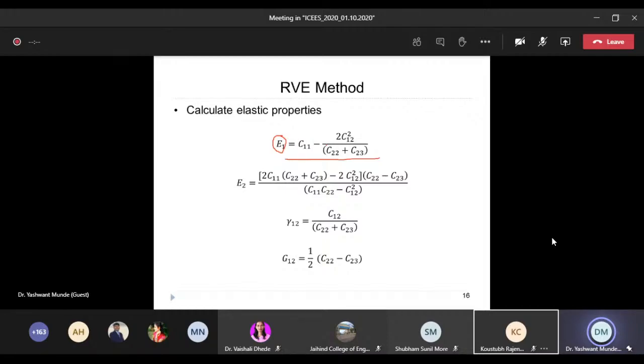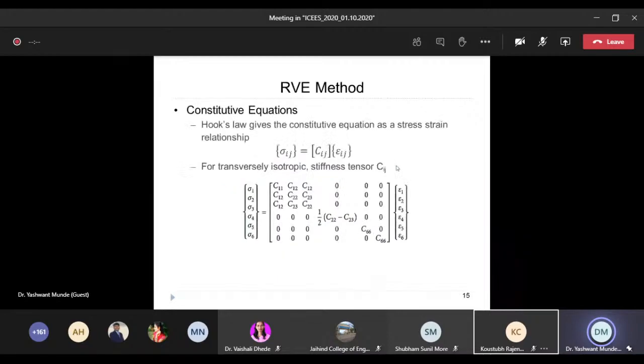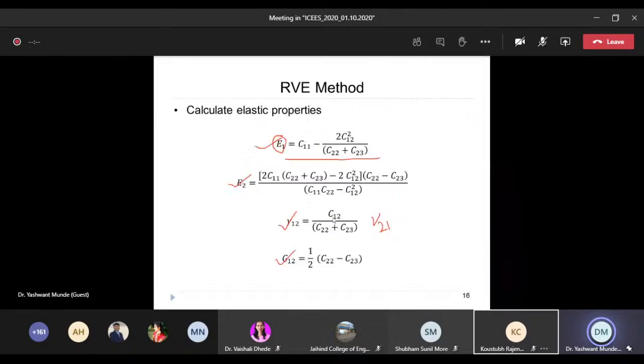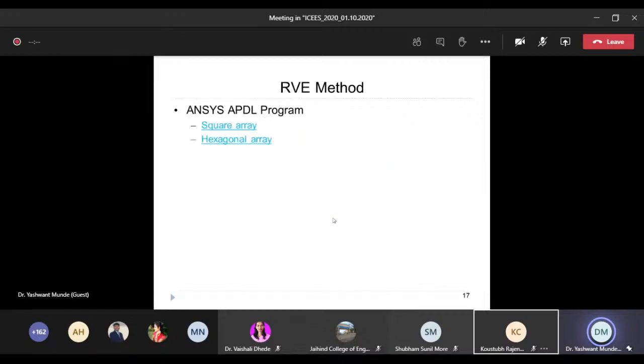And those CIJ coefficients we use to calculate the elastic properties of the composite material. That is E1, the elastic property of the material in direction 1, E2, the modulus in direction 2, mu12, Poisson's ratio in plane 1-2, and the shear modulus in plane 1-2. And once you know E1, E2, mu12, G12, you can also calculate mu21, the other Poisson's ratio. So these are the 5 elastic properties we can calculate. This is an example for a transversely isotropic material, where we have only 5 elastic constants. With the same methodology, we can adopt it for orthotropic material, monoclinic material, and isotropic material. So this is all about the methodology.